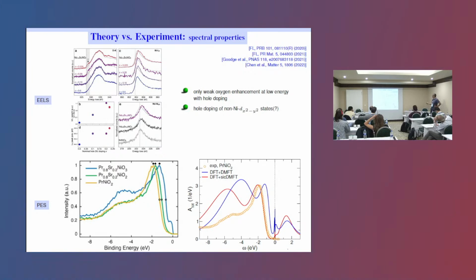So the red curve is DFT plus sicDMFT with the correlation with oxygen. The blue one is the pure DFT DMFT with the same U. And you see the comparisons rather nice. So again, this red curve is the prediction 2 years earlier, and that is the measurement. And you see the peaks perfectly more or less agree with each other.